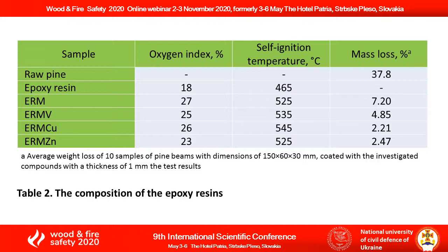Modification of the ERM composition with transition metal oxides increases the flammability resistance of the coating to oxygen index values of 25, 26 and 23% for ERMV, ERMCu and ERMZn compositions accordingly. But at the same time, the average weight loss of samples decreases and is 4.85, 2.21 and 2.47 for compositions ERMV, ERMCu and ERMZn.